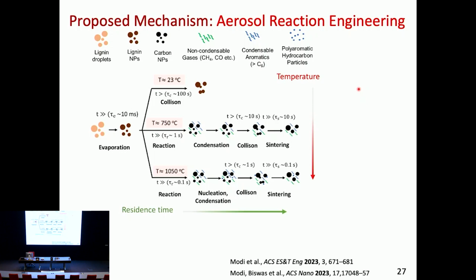So just to show you some examples, let's start with a lignin droplet. If I run it at room temperature, 23 degrees Celsius, let's say, it's not going to decompose chemically, it's low temperature, but the lignin droplet will dry out. I might get a lignin nanoparticle depending on the concentration I start with. I can have collisional growth. Remember those collisional characteristic times. I will have collisional growth if the residence time, that little t is the residence time, is greater than the collisional characteristic time.